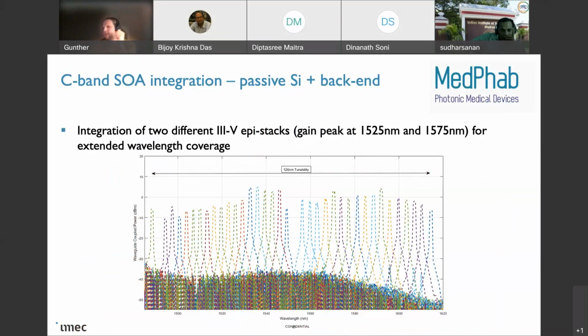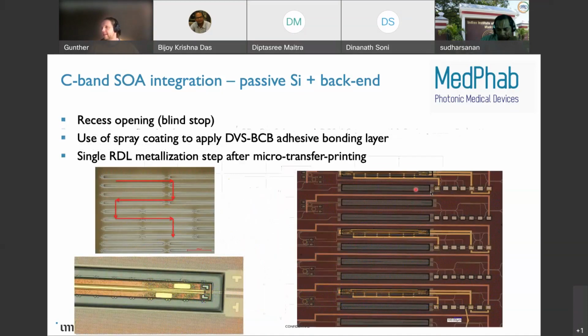So using that approach, we recently integrated two different III-V SOAs on the same photonic IC right next to each other, one with a gain peak at 1525 and one with a gain peak at 1575. And this way together we could cover a tuning range of about 125 nanometers. So this also shows you the strength of microtransfer printing, that you can very intimately integrate different III-V components on a single photonic integrated circuit.